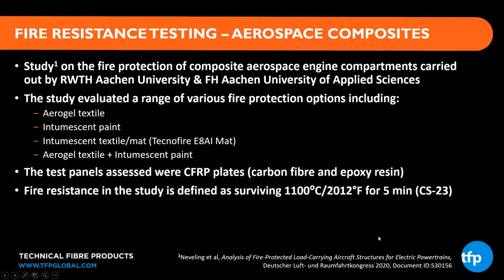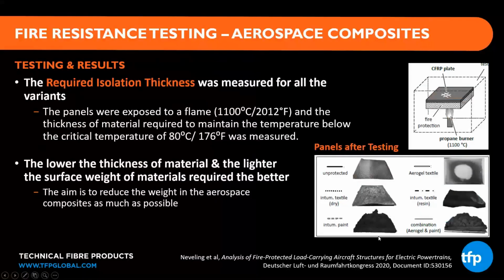So we're going to look at some breakdowns of some photos on this next slide, where you can see the test mechanism, the test setup on the right, which that CFRP plate is located, and there's a flame impinging from the bottom. Now we're trying to measure the cold side temperature on that plate, and the thickness criterion was to isolate these panels where they're exposed to an 1100 C flame, but the cold side temperature, the critical temperature, would be 80 C. So we can't rise above 80 C. That would be considered a failure.